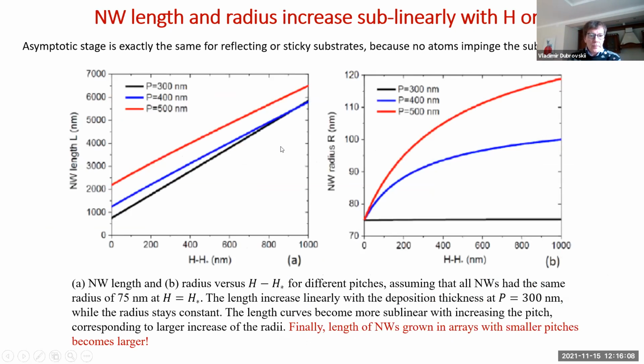So I can produce these length-time curves in the asymptotic stage. What I see is that both length and radius increase sublinearly, and that's what most people see in the growth kinetics, where both axial and radial growth are included. For larger pitches, of course, the radius grows much faster, while for 300 nanometer pitch, it stays constant, basically. So there is no radial growth. For larger pitch, it increases. And as a consequence, the length becomes more and more sublinear. And finally, the curves cross. So finally, the nanowire grown in a larger array pitch becomes shorter than the one grown in a smaller one.